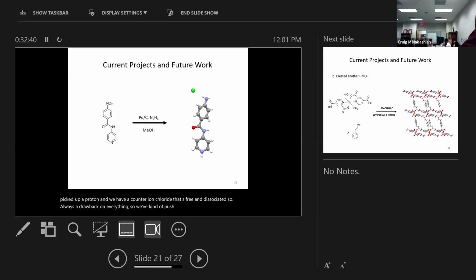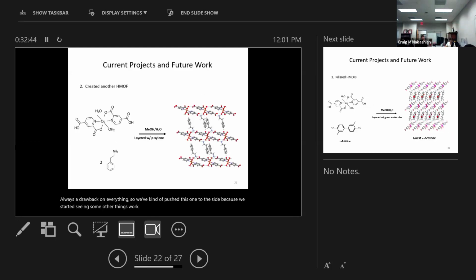So we've kind of pushed this one to the side because we started seeing some other things work, like this framework, which is very similar to what we've seen in the past. It is the copper based, but instead of using what was called alpha-methylbenzylamine, we're now using what's called phenethylamine. So we extended the carbon distance between the aromatic molecule and the NH2. And what happens? One carbon bond difference. We went from an ABA layer to now an AB, because now this becomes our repeating pattern. Layer, interlayer, layer, interlayer. So that's an AB pattern. So one carbon-carbon bond difference, and we generated a completely different framework, right? And as you can see, our phenethylamine molecule is right inside of the interlayer.